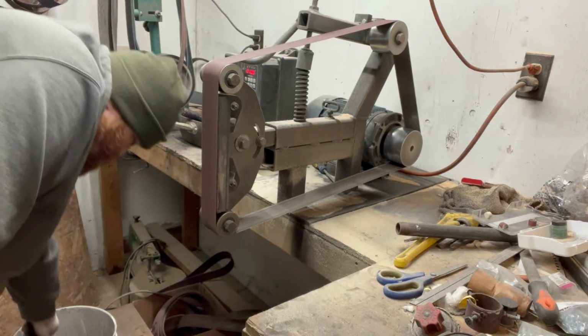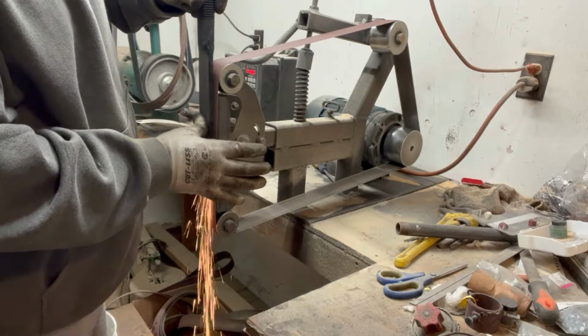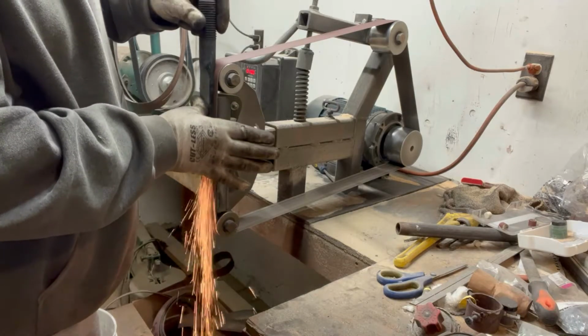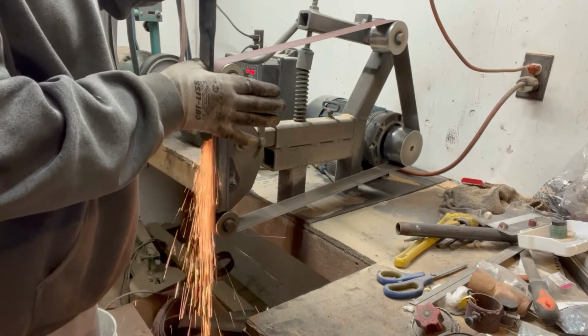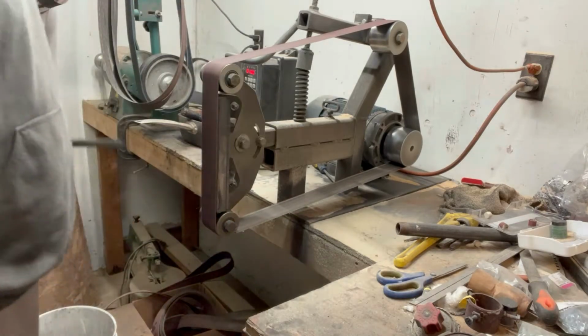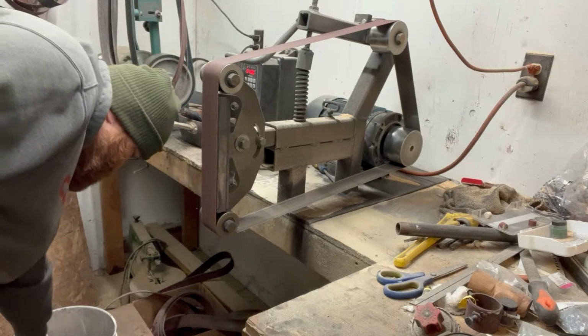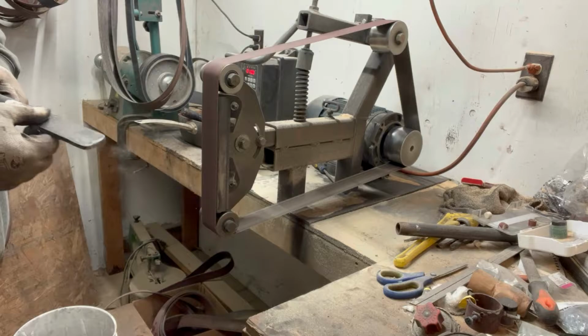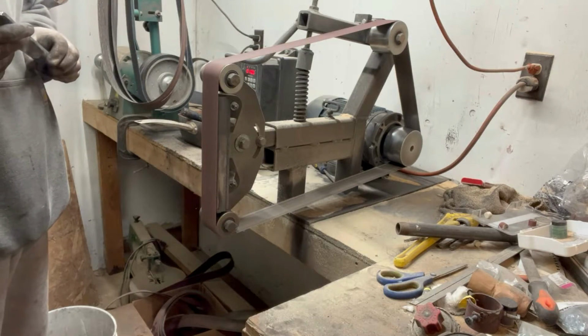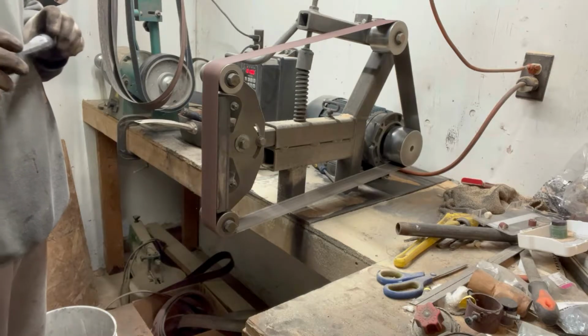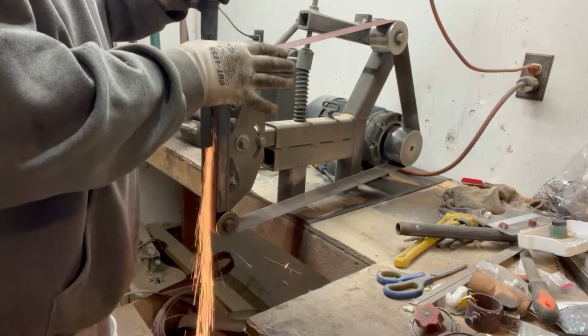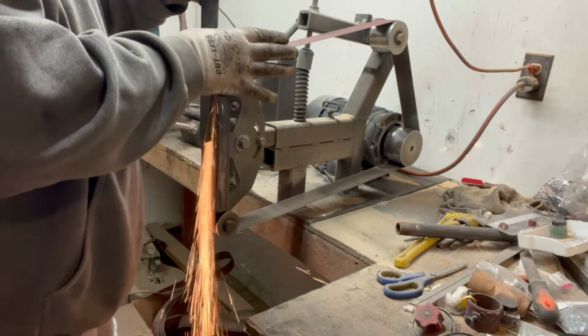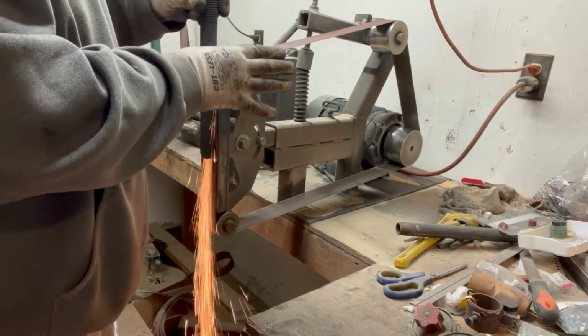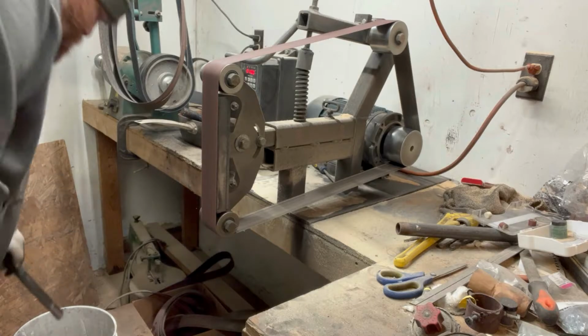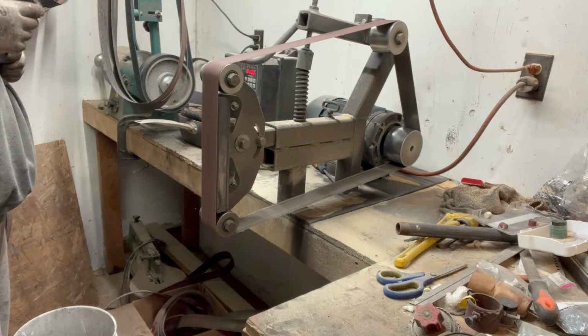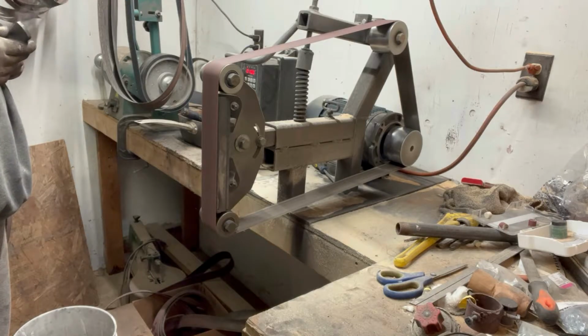If you really want to be scientific about it, get yourself some vermiculite or some kitty litter, and heat your piece up to critical temperature, and then bury that piece with at least 4 inches of clay-based litter above your heated zone, above and below, and sides. And let it cool completely. You can also bury them in the ground too. Do the same thing with sand or dirt. When I had a dirt floor, I would do that. I would just channel everything out underneath the forge, and then when I needed to anneal something, I would just bury it in the ground. Just let it cool down.